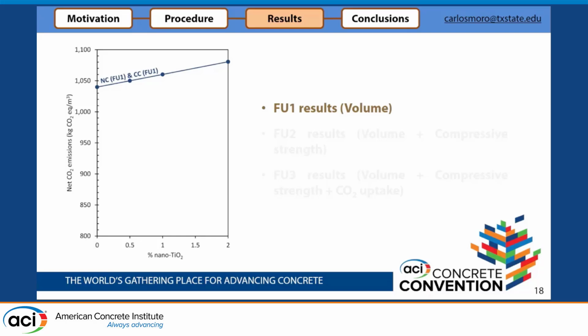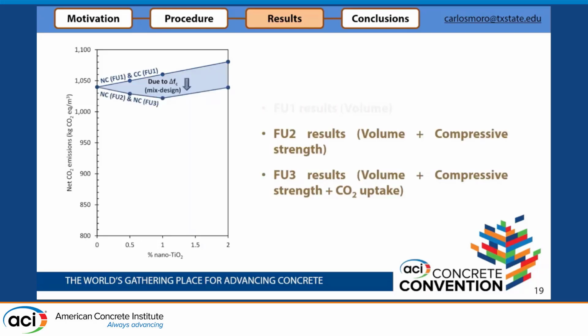And we can see that the nanoparticles increase the global warming potential because the production of nanotitanium dioxide emits a lot of CO2. But if we use other functional units like volume and compressive strength, for example, for the normal cure, we can see that the nanoparticles actually decrease the CO2 emissions or the global warming potential associated with that. Why? Because it improves the compressive strength, right? So we can lower the amount of cement that we are using, and indeed, instead of having a bad effect in the environment, we'll have a good effect because of the lower cement content that we need to use.